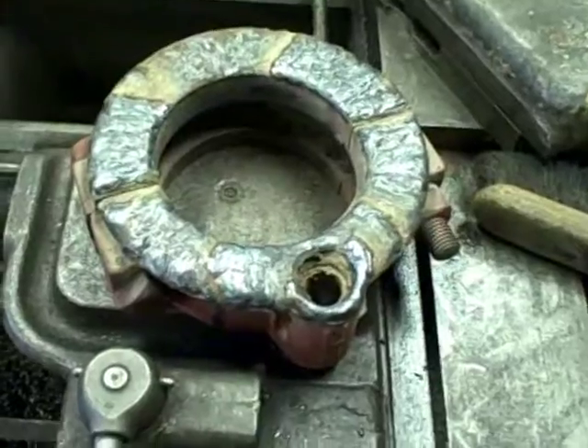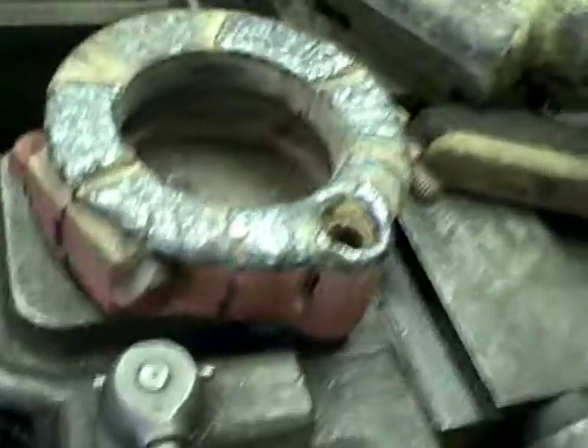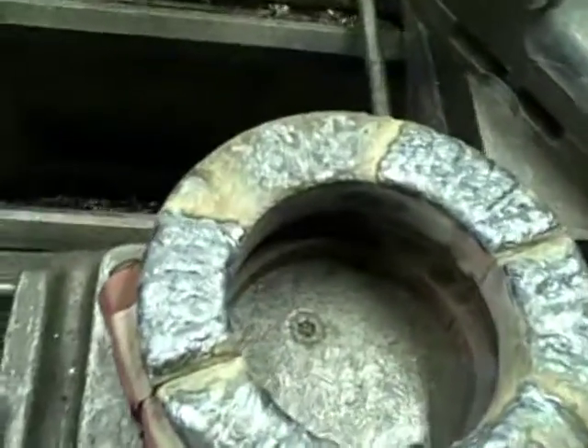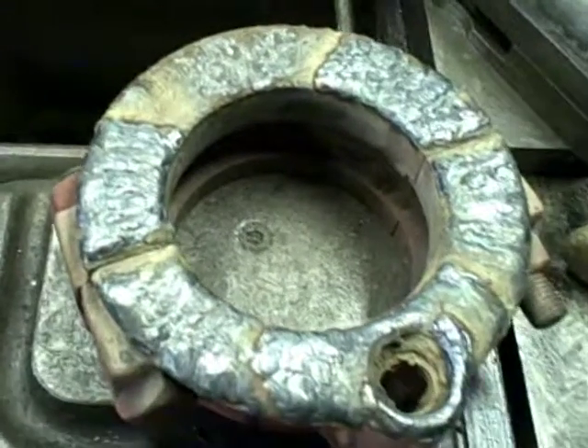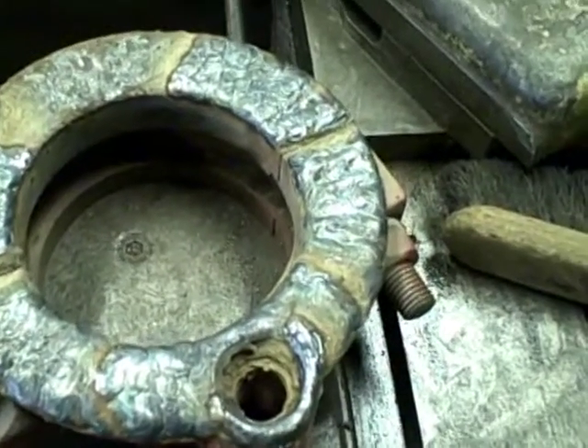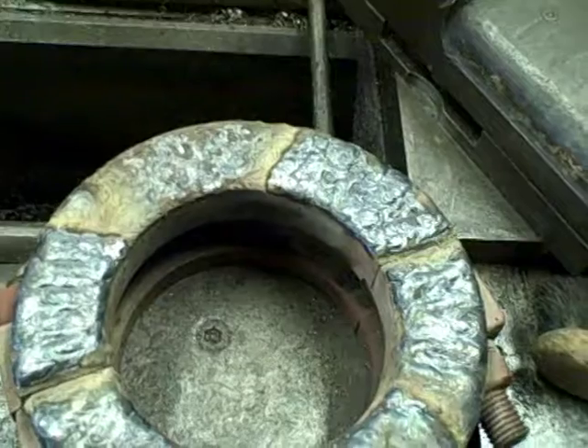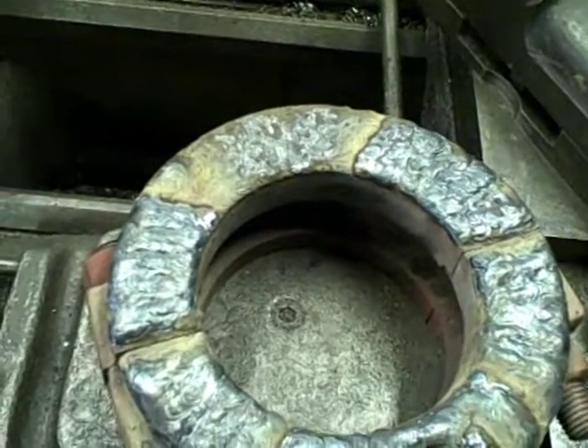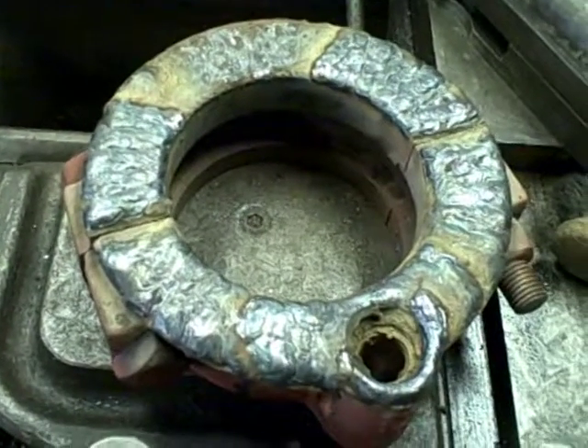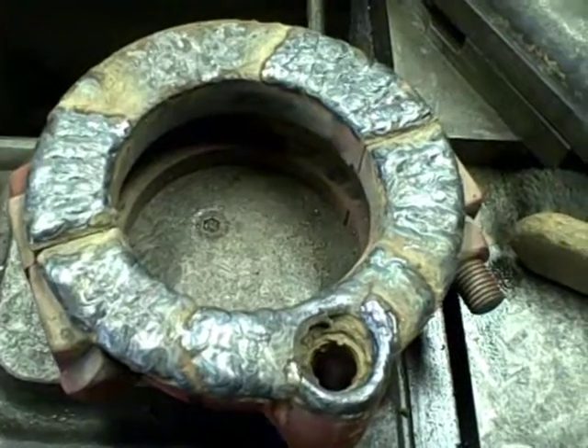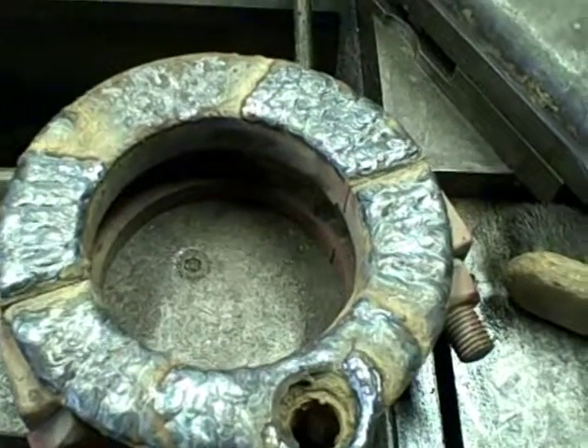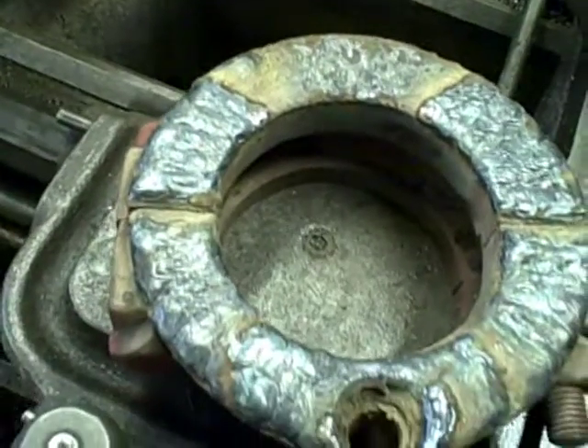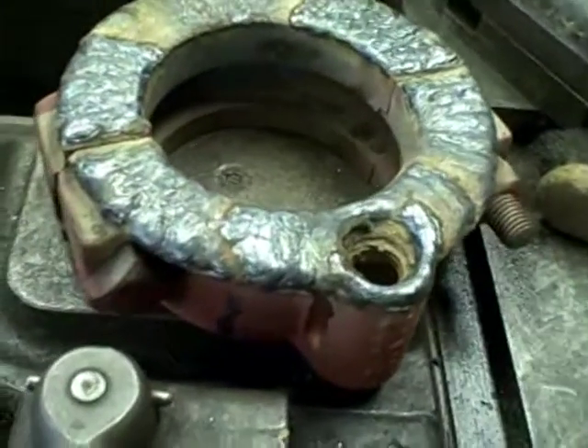Okay, in this video, this is another one of those axle rings that's been built up by weld, but we had a little dilemma when we put them onto the forge to heat them up to 1500 degrees. What had happened was we couldn't control the heat very well. So the oils in the casting had blown out and pitted through and blew holes into the casting when the oil was expelled out in the high temperature.